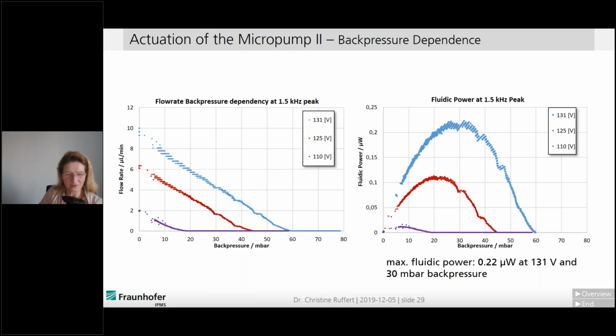There are some further measurement curves from the lab I want to share with you. We have the flow rate in microliter per minute dependent on the back pressure in millibar on the left-hand side, and this is for the peak at 1.5 kilohertz we saw on the slide before, also for 3 voltage values. On the right-hand side, you see the fluidic power in microwatts, depending on the back pressure in millibar, also the 3 curves for the 3 voltage values. We see the maximal fluidic power measured in the lab with our micropump at 0.22 microwatts at an exciting voltage of 131 volts and 30 millibar back pressure.